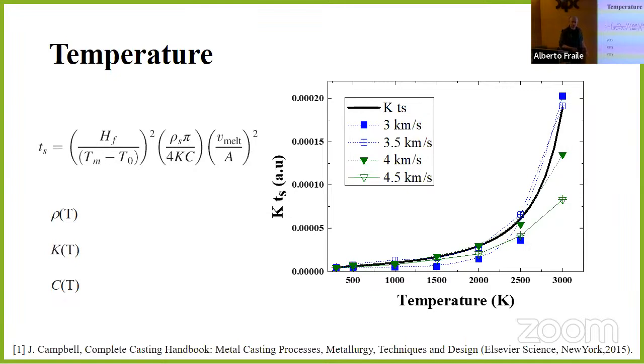So with the temperature, you refer to the temperature of the particles or also to your wall? The temperature of the target. Target only. Yeah, before the impact, I mean, not after the impact. And the particle itself, we could do that as well. In all the simulations, the target and the particle are at the same temperature, 300K. Then you do the impact, and when we talk about temperature here, it is the temperature of the target that is different. But we could do the reverse, that's true.